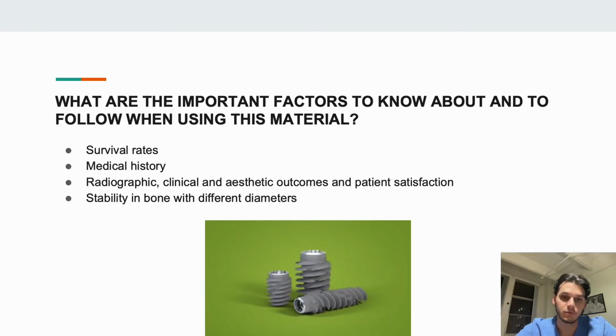What are the important factors to know about and to follow when using this material? So long-term dental implant survival rate, it's a very important one. It said that the long-term survival rate for a period of 12.2 to 23.5 years was found to be 88.02% for Straumann dental implants, and a portion of 82.8% of patients with implant losses had a medical history of periodontitis.